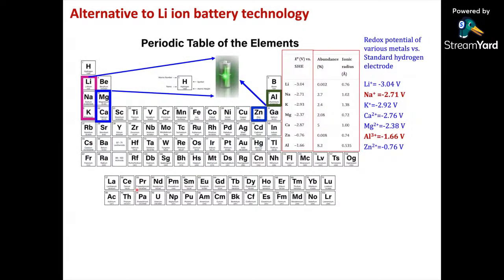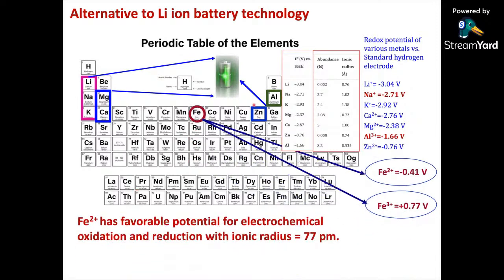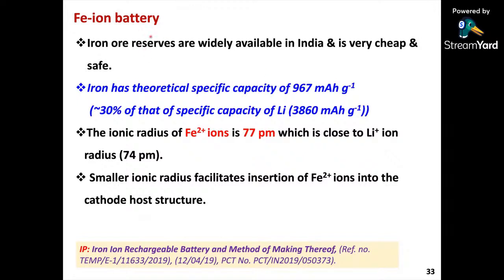Then we go to the alternative to lithium-ion battery, mainly metal anode batteries. One of the metal anode batteries uses Fe2+. So we know that for an iron ion battery, iron ore is plentifully available in our country, and it has a specific capacity of very close to 1000 milliampere hour per gram, which is 30% of the specific capacity of lithium. And the most interesting thing is Fe2+ has an ionic radius of 77 picometer, which is close to lithium ion, 74 pm.